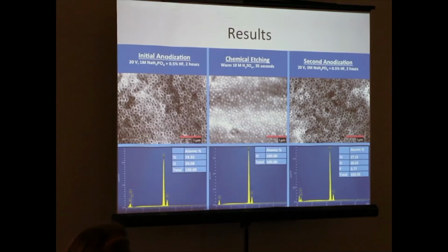And while you would believe that it would be a 2-to-1 ratio of oxygen to titanium, since it's titanium dioxide, we actually see that there's more titanium in the sample just because our oxide layer is very thin, and the X-rays are actually penetrating past the oxide layer into the sample. So that's why there's a higher amount of titanium than oxygen. And this scale bar right here is about 1 micrometer. These nanopores, I have measured them before, I didn't put that picture up, but they're roughly 80 nanometers in diameter.